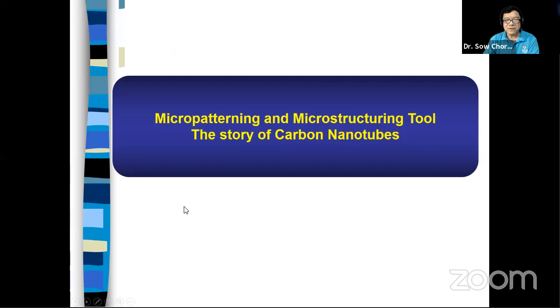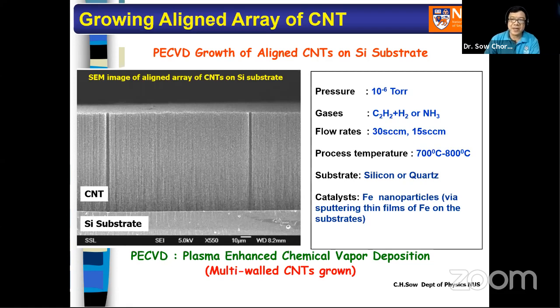Next slide. First, I'm going to tell you the story of microstructuring of carbon nanotubes. We grow our own carbon nanotubes, an aligned array of multiwall carbon nanotubes, using the PECVD technique. The silicon substrate is typically seeded with iron catalyst. Then in the PECVD chamber, we use acetylene gas, sometimes mixed with ammonia or hydrogen. Basically, it breaks up into carbon and hydrogen radicals, and the carbon finds the iron nanoparticles on the surface of the silicon, and they grow a nice aligned array of carbon nanotubes, as you can see in the SEM picture here. It's very nice. You have a nano carpet that you can play around with. What we do is take this nano carpet and put it on top of the sample stage of the optical microscope.